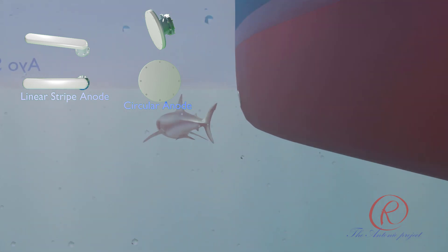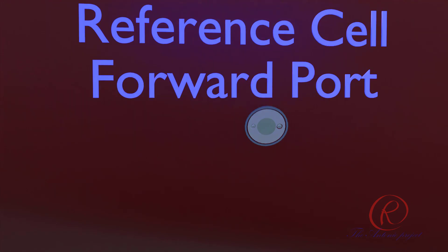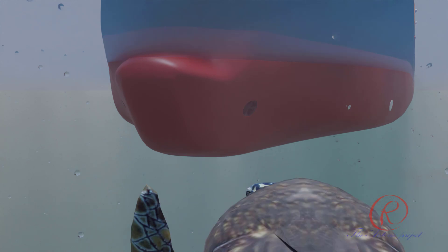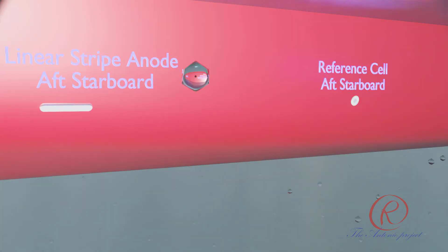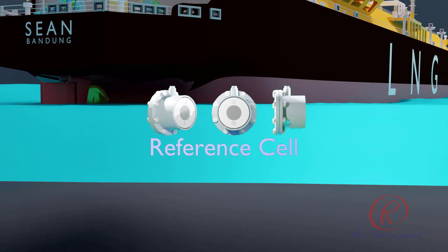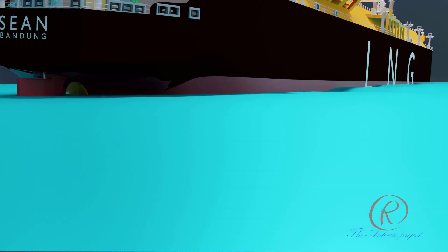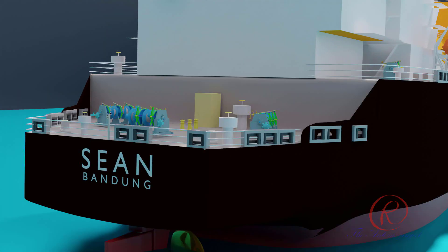The application of ICCP on ships protects the hull from corrosion. The ICCP system consists of the following parts. Impressed current anodes: these are usually made of strong inert material like titanium and may be disc or strip shaped. Either 2 or 4 units are placed symmetrically forward and aft of the vessel. The anodes are welded onto doubler plates on the hull surface, flush with the outside hull plate. This anode material serves only as a source of electrons to the hull and is not consumed in providing this protective current. Reference cells: the electrical potential is monitored by a reference electrode assembly fitted port and starboard between the anodes, where the lowest possible potential is likely to occur, so as to detect the slightest corrosion current between hull and sea water.